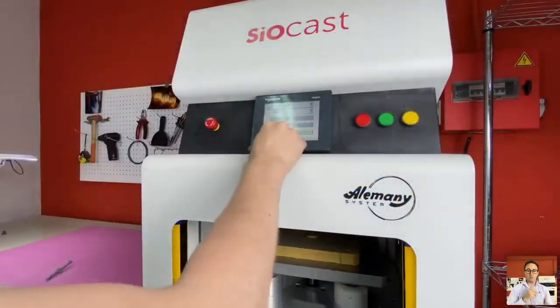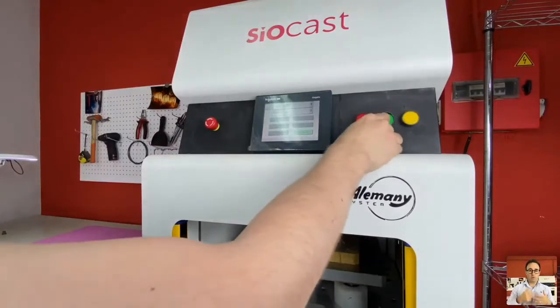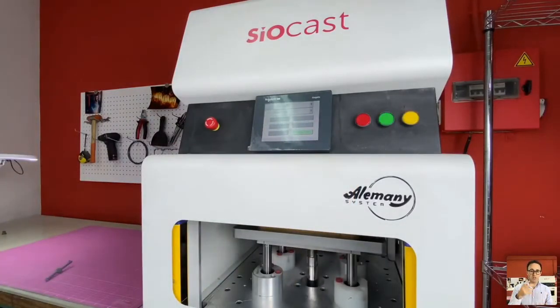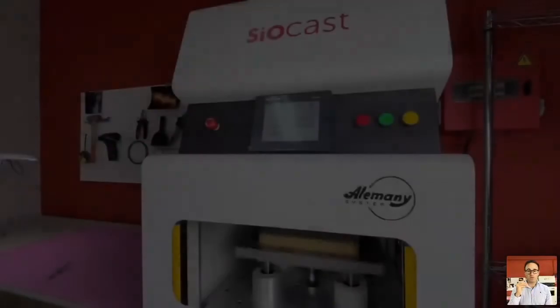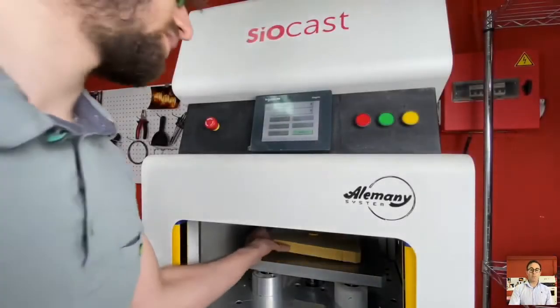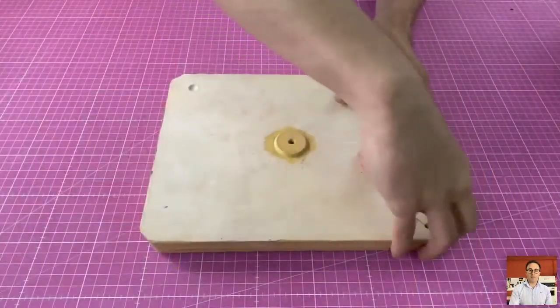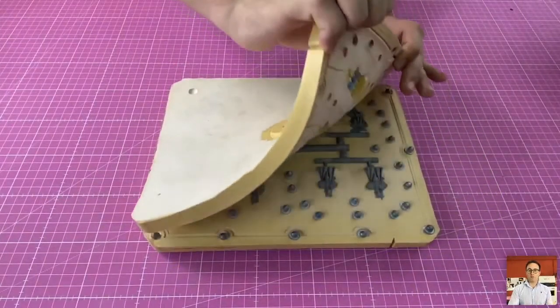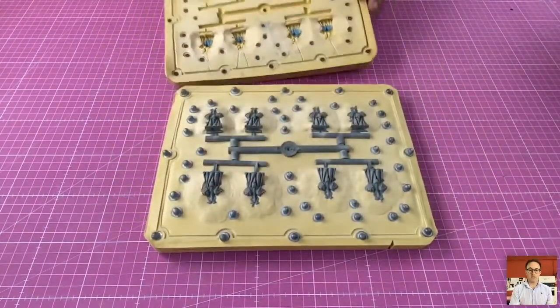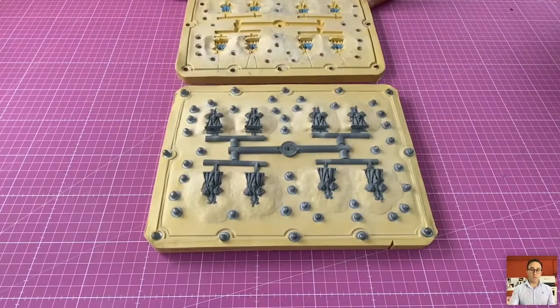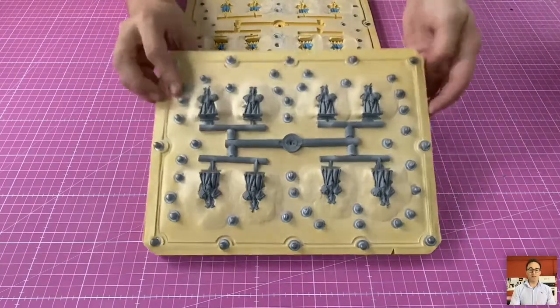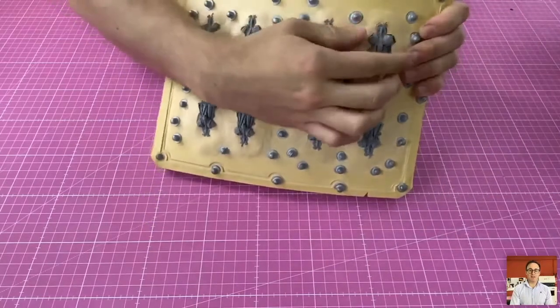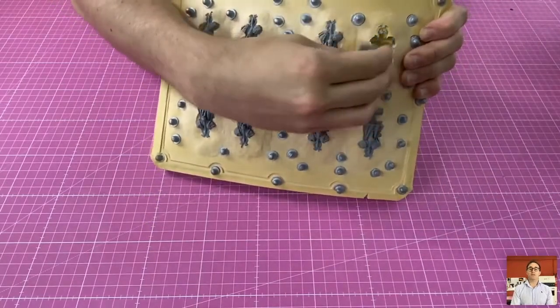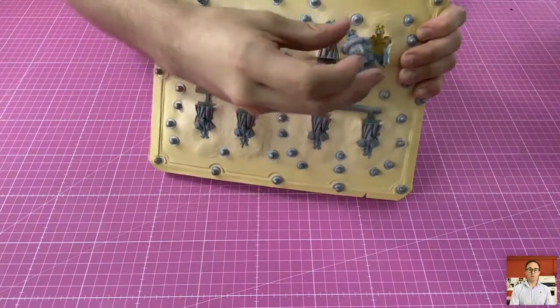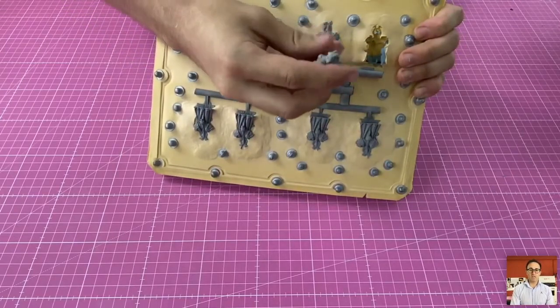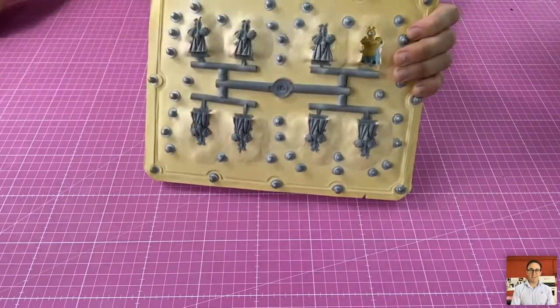So here we start with the technique that we teach, we proceed with opening the gates or playing with the injection parameters until we have the mold already set up. Depending on the part complexity, this would take between 5 to 15 castings. So in less than, let's say, 1 hour, you already have the mold perfectly balanced and ready for production. You can see here that this mold, after 7 shots, was perfectly set up.